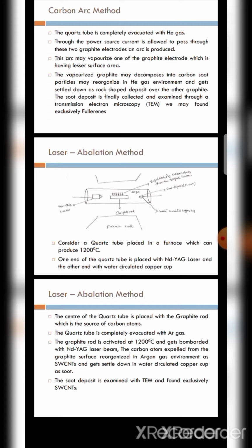The carbon atoms expelled from the graphite surface are reorganized in the argon gas environment as single-wall carbon nanotubes and settle down in the water-circulated copper cup as soot. The soot deposited is examined with TEM and found to be exclusively single-wall carbon nanotubes.